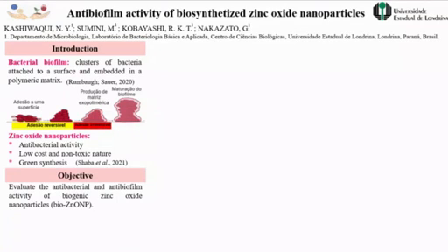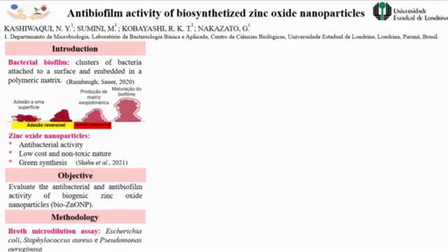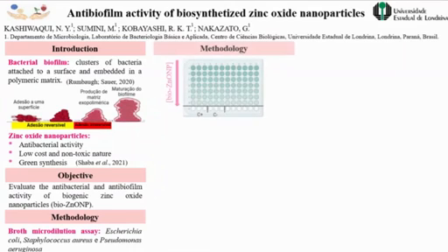First, the zinc oxide nanoparticles were synthesized using avocado leaf extract, and then its antibacterial activity was evaluated by the broth microdilution assay against Escherichia coli, Staphylococcus aureus, and Pseudomonas aeruginosa. In this assay, we tested different concentrations of the nanoparticles and, by observing the bacterial growth, we've determined the minimum inhibitory concentration, also known as MIC, which is the minimum concentration of the treatment capable of inhibiting the bacterial growth.